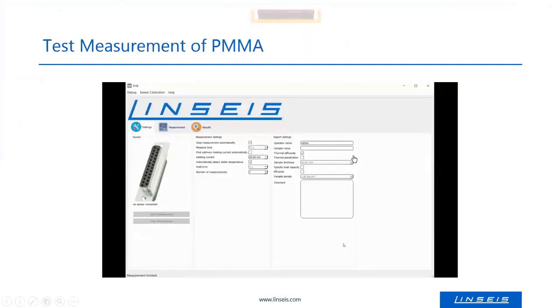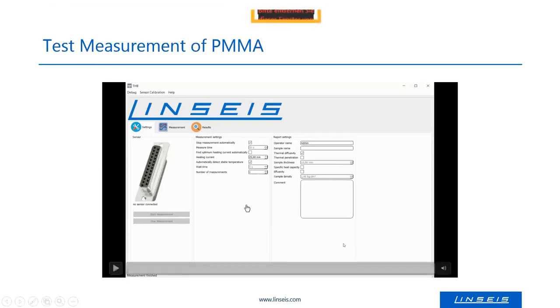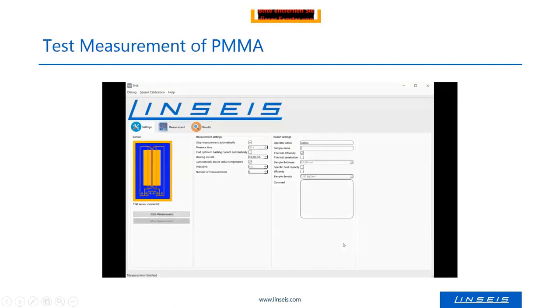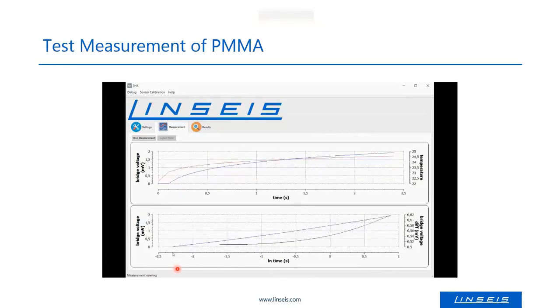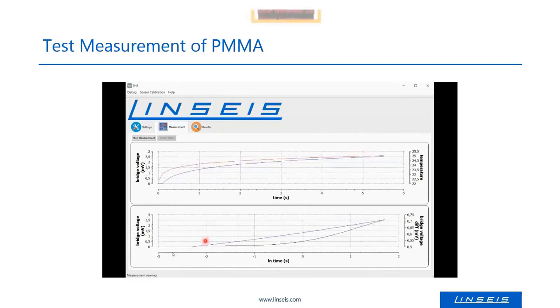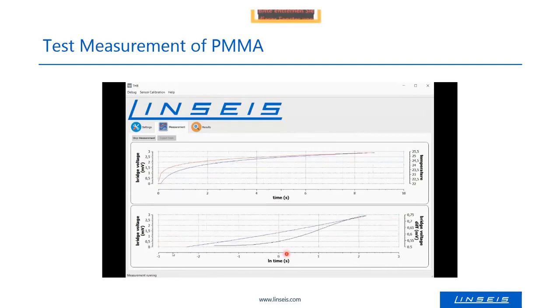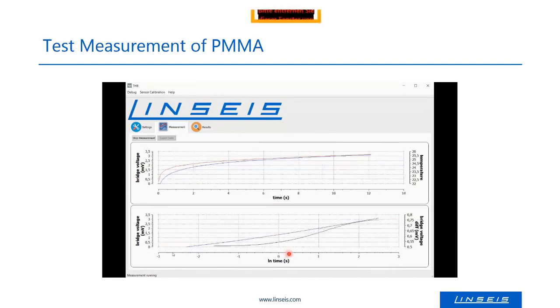I will show you now a real measurement, which we did with the THB Advanced in our lab. So I start the measurement and you will see the sensor is found now by the instrument. Here, the sample name, it's a plastic material, is typed in. The hook is set for automatic measurement and the measurement is started. It took 2 or 3 seconds to find the optimum current. And now the measurement is running, and the instrument detects automatically the end of the measurement when enough data are there to stop it.